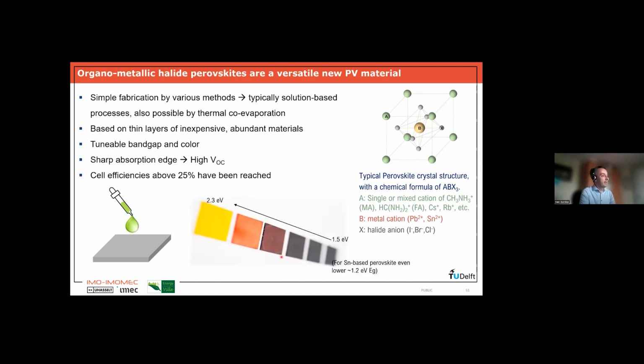Moreover, it has a tunable band gap, as is shown here. So by changing the composition, you can change the band gap. And it typically leads to very high VOCs. Many research groups have already achieved efficiencies above 25%, which is really quite impressive for a single junction device. So all of this makes it a very interesting material to put on top of silicon solar cells in tandems. Now, the silicon and the perovskites can be combined in a tandem structure in different ways.